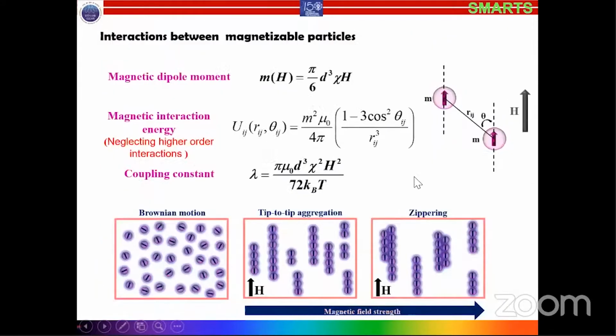And the beauty of the system is you can tune the interaction using a magnetic field. It can induce a magnetic moment which is proportional to the applied magnetic field. That's what you see in this equation. And the magnetic interaction energy, again, you can tune with a magnetic field. The dimensionless factor used to explain the order-disorder transition is the coupling constant, lambda, which is the ratio of the magnetic to the thermal energy. When this ratio is less than 1, you see Brownian motion of the particles. That's what you saw in the microscopic picture.